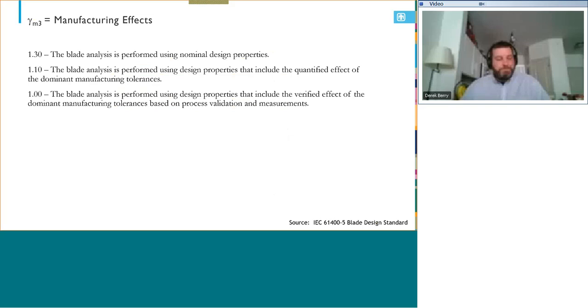In terms of manufacturing effects, and this is going back again to the wind blade design standard, we have a range of possibilities for this exact partial safety factor. It can go all the way from something like 1.3, if you're using literature to look up flaw impacts, all the way down to maybe 1 if you've actually fully characterized the effect of a flaw on the strength or fatigue resistance of your material and structure.